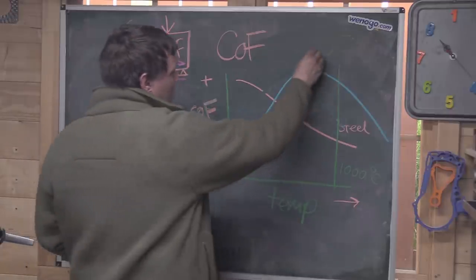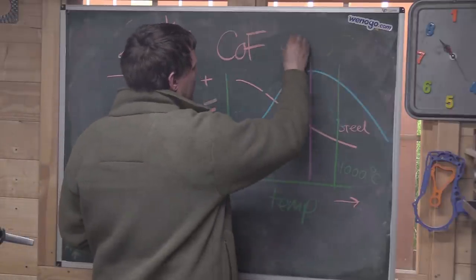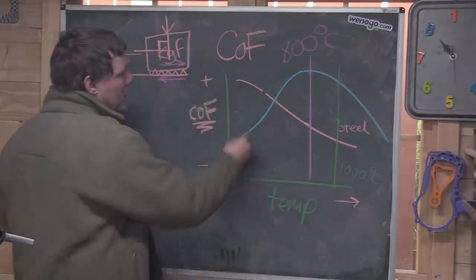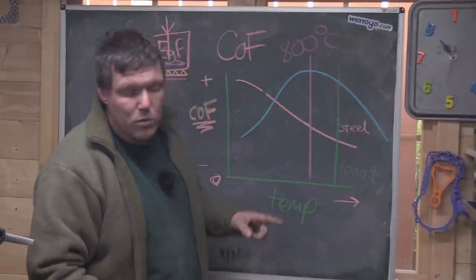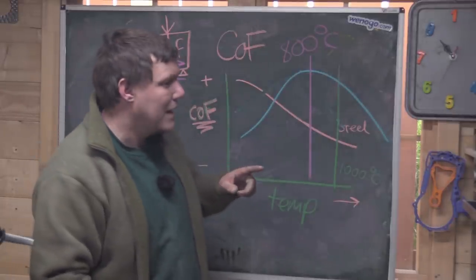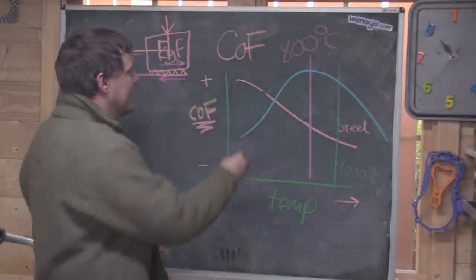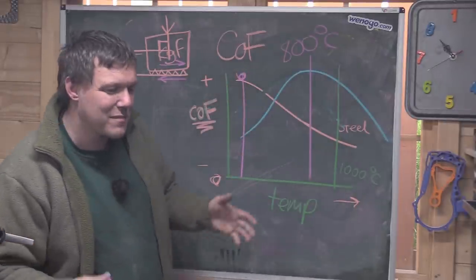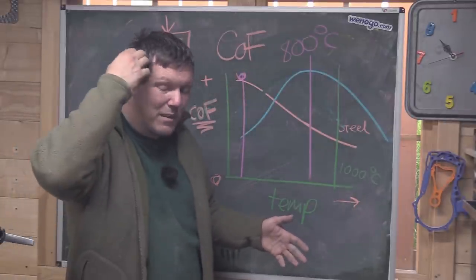So you pick just up here and say that's 800 degrees C. Your carbon ones are a lot better. Lower down they don't kick in. This is why in MotoGP you'll see them using cast iron, because cast iron is really good at lower temperatures, especially when it's wet, because that's the problem, you're constantly getting the discs wet which cools them down.